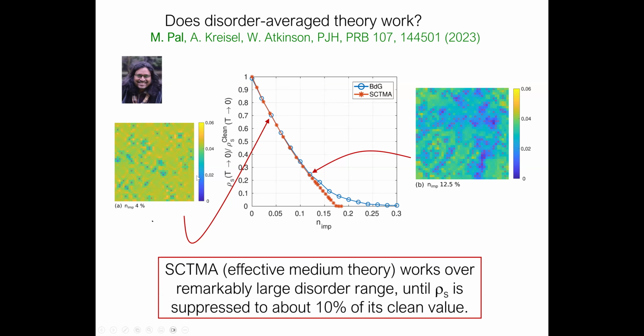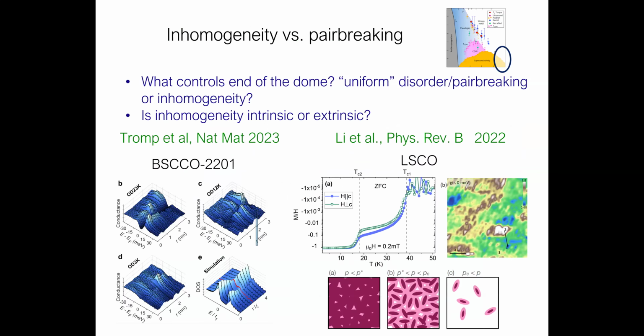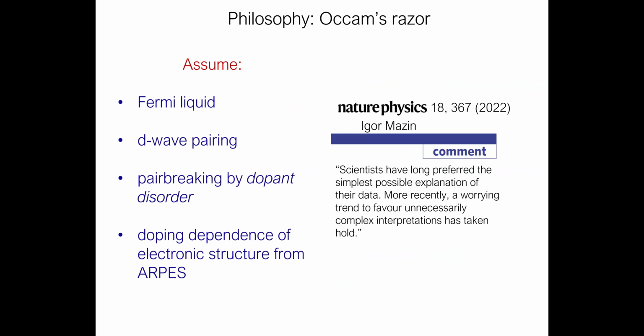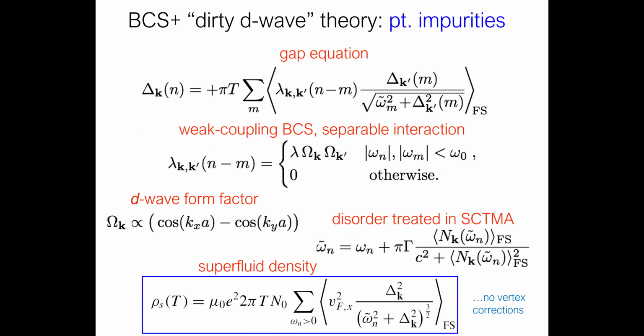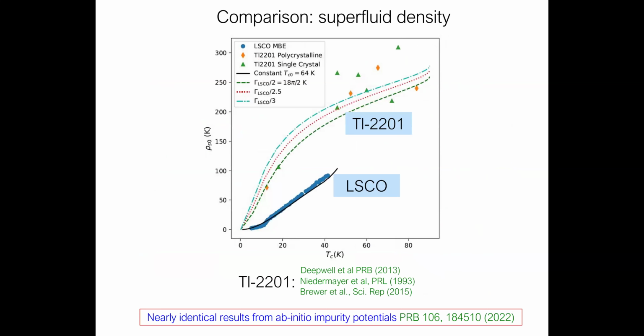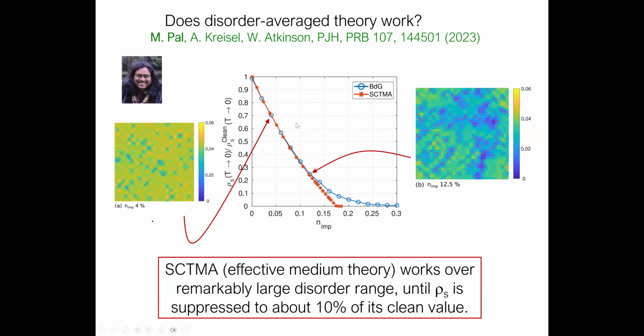And we looked at two calculations. One is a Bogoliubov-de Gennes simulation, which takes into account self-consistently the suppression of the order parameter around each impurity and the interference of those effects. And the other is a disorder averaged SCTMA calculation. That's self-consistent T-matrix approximation. And all these equations that I showed you are based on the assumption of an effective medium approach where the disorder is averaged over. And so that's what I'm testing here. And the question we asked was, to what extent can this theory be trusted when you have an inhomogeneous system?